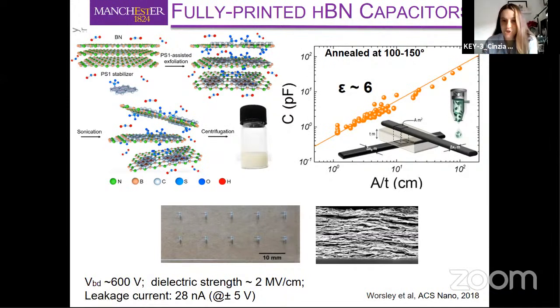And because we're using a inkjet printer, we can change the area and the thickness of the capacitor as we want. So we can span a very large range of capacitance, and we can even connect those capacitors that you can see here in parallel to further increase the capacitance with the inkjet printer very easily. And so in this way, we've been able basically to fully characterize the electric properties of this boron nitride ink. And so we know the dielectric constant, the breakdown voltage, and so on.